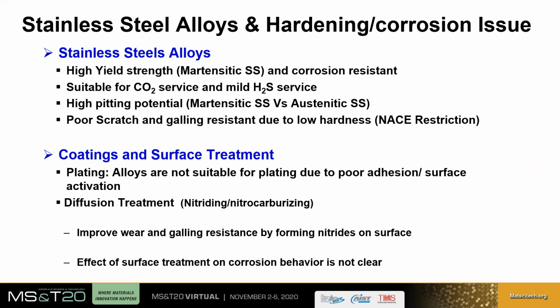In such environment, we need high strength corrosion resistant alloy for short to long services depending upon the operating conditions. In order to operate effectively at low cost, stainless steels are preferred in CO2 and mild H2S environment. For example, 13 chrome and super 13 chrome and 17-4 PH stainless steel are high in yield strength and high in pitting potential than low alloy steels. However, they are not good in galling, wear and scratch resistance due to low hardness, and they get damaged during assembly and during operation. Therefore, these alloys are often plated with electroless nickel and copper, which eventually flakes off during operation due to poor adhesion.